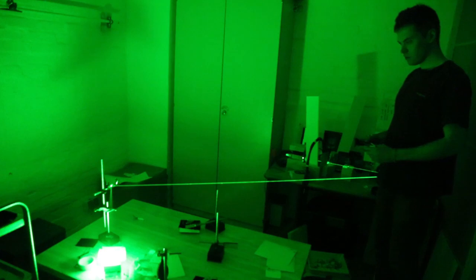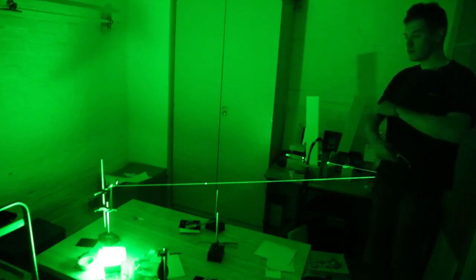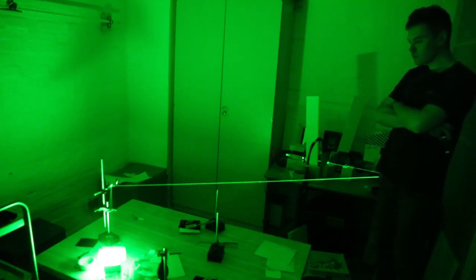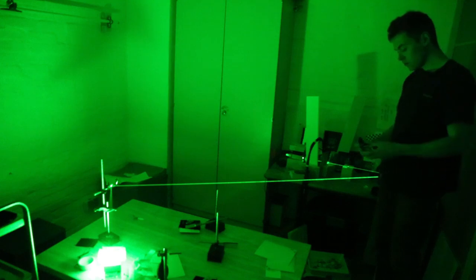You want to turn it until you see the least reflection bouncing off your glass plate and the most light passing through. The plate is exposed for 4 minutes and then left in the dark for 5 minutes. This is called the dark reaction and can be extended up to 3 hours,